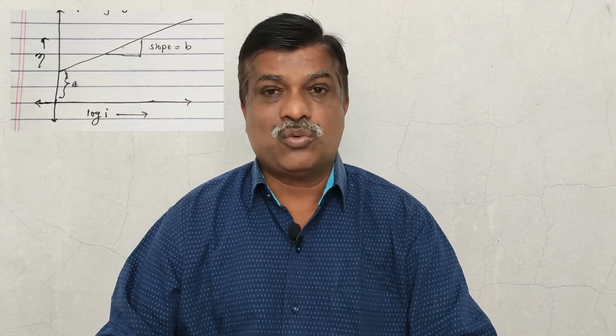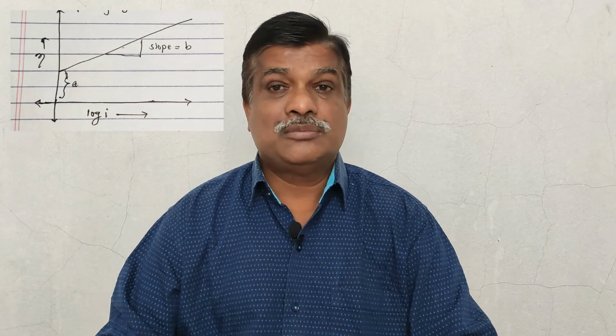b is equal to 2.303 RT divided by alpha F, which is equal to 0.1184, approximately 0.12 volt at 298 Kelvin. b is equal to the slope, where alpha can have values between 0.2 and 1. The equation is of the type y is equal to mx plus c, that is, y is equal to c plus mx.